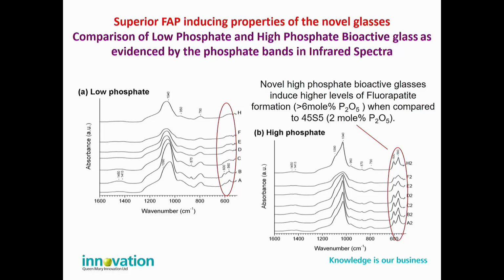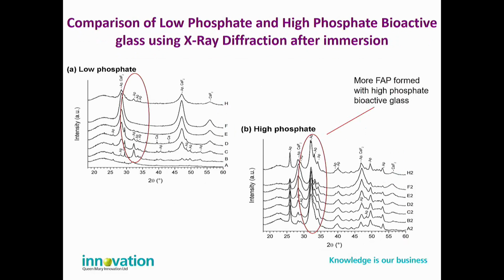We can see the effects of using a low phosphate or a high phosphate glass in this data here. These are Fourier transform infrared spectra, and as we go from A to F, we're increasing the calcium fluoride content. You can see with the low phosphate glasses to the left, in the circled area, the peaks are weak and they disappear fairly quickly, whereas on the high phosphate bioglasses to the right, the peaks are much more intense for the PO stretching bands of apatite. So with higher phosphate contents, we form much more apatite.